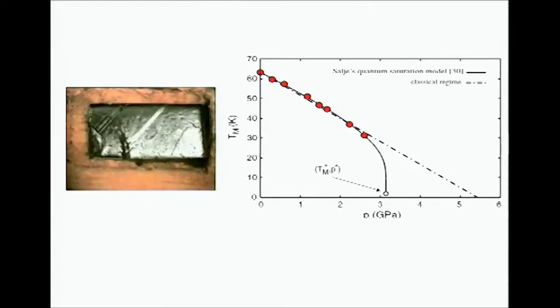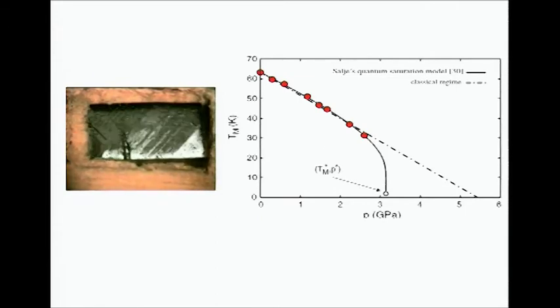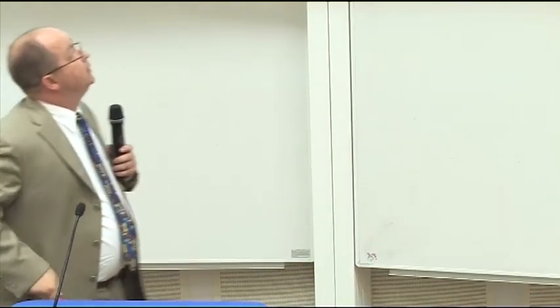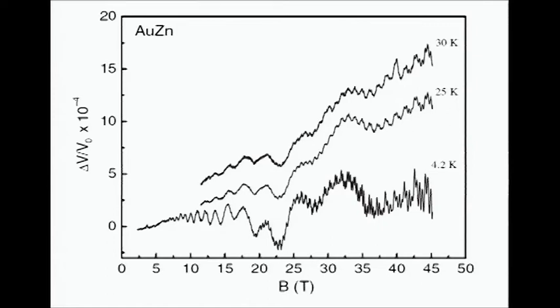So you can take this a step further, and I began to look at electronic structure probes. The traditional ways, of course, are de Haas van Alphen and Shubnikov de Haas. This experiment was on a shape memory alloy, and I actually saw quantum oscillations in the speed of sound because I wanted a different probe to work in high magnetic fields.